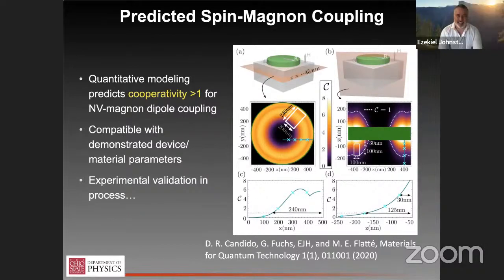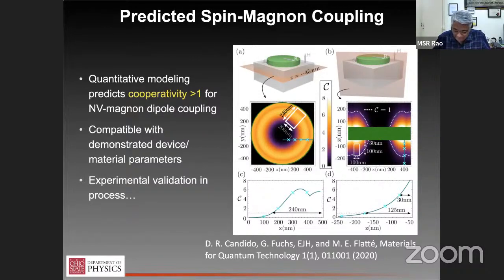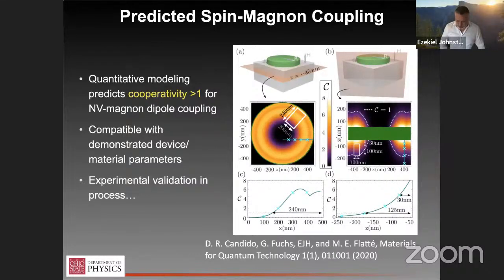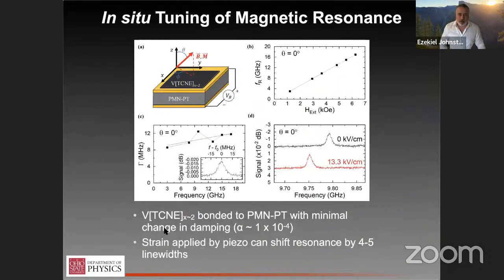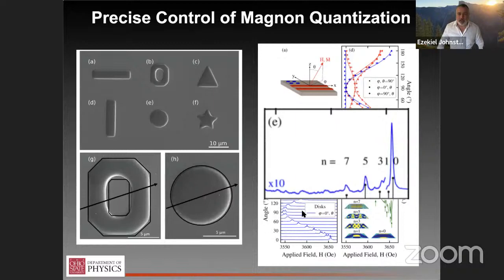Yeah. Okay, that's good. So my other question is, so the magnon detection that you see in VTCNE, is it thickness dependent? You see any dependence of the thickness of the FMR signal? Yes. Come back to this data. Okay. So this is the FMR signal from an array of disks. And I mentioned that these are essentially harmonics of the fundamental mode, excited, higher level quantized states. So for these disks, it's a 3D quantization, right? So you have a lateral confinement from the perimeter of the disk and a thickness confinement.